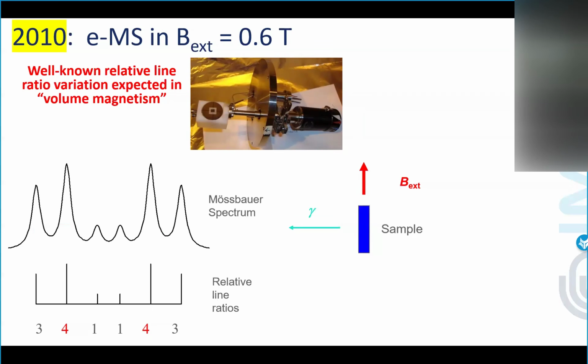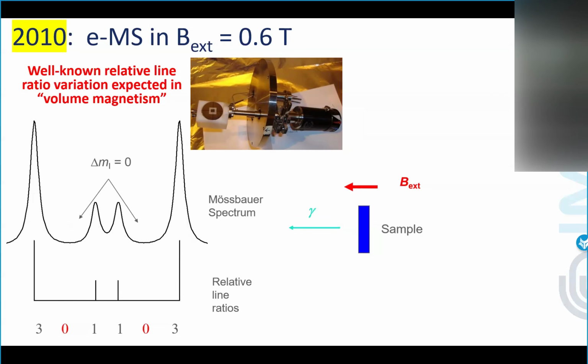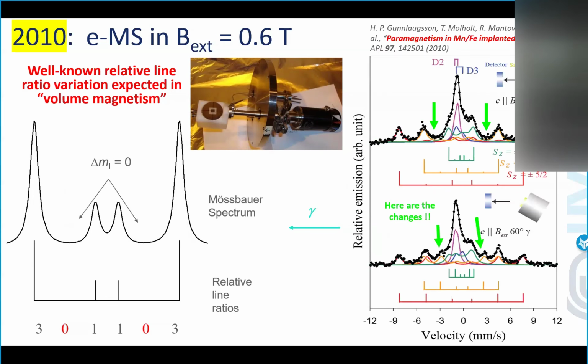As was explained this morning already, in the case of long-range magnetic interaction, so volume magnetism, real dilute magnetism, you would see, as far as you go parallel with your externally applied magnetic field to the gamma, a collapse of the inner lines from 3-4-1 to 3-0-1. Of course, we cannot do exactly 0 and 90 degrees, but there is an angle in between. The theory is quite well accepted there, and this is what we measured. So look at the middle lines. They were not collapsing when we moved to the parallel configuration. But what happened was very clearly pointing to other things.